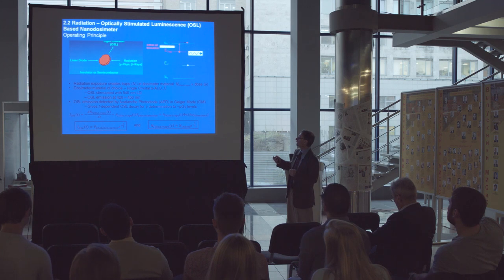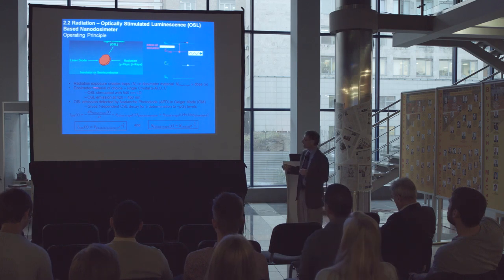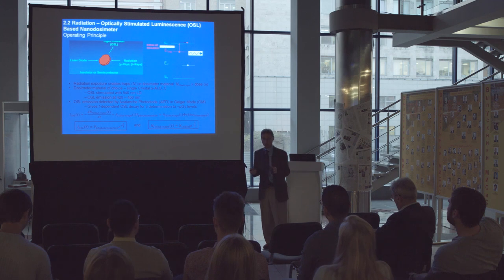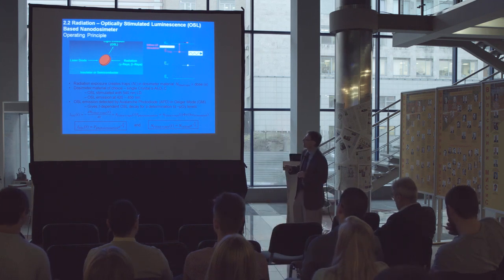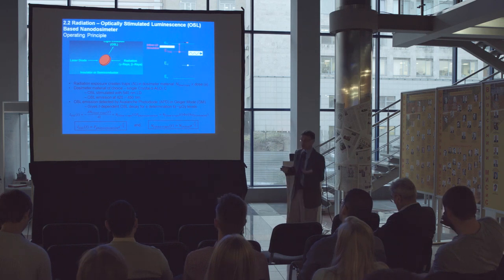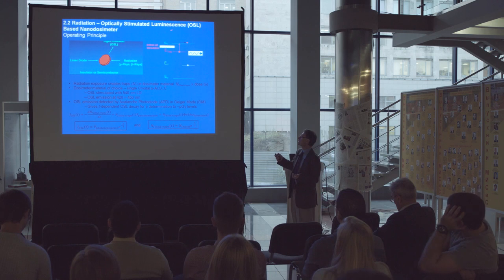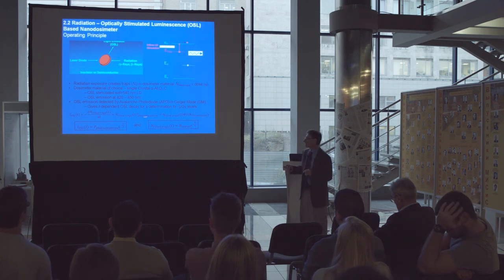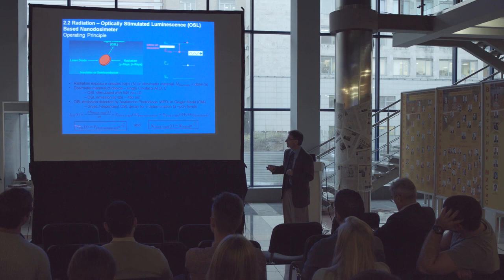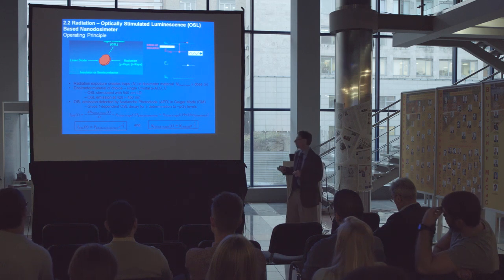Right. So I stimulate with low energy light, for example here, this 540 nanometer light, and the emitted light is higher energy, which means shorter wavelength. We call that optically stimulated luminescence, and it's around 420 to 450. The basic principle is that the rate of change of the number density of filled traps, every time one photoionizes and we capture its carrier in the light-emitting recombination process, we end up with light. So that's the probability of photoionization times the number of filled traps, with the intensity, right? There's a little differential equation here, which we can solve, which means the intensity of the stimulated luminescence as a function of time will be exponentially dependent on time, with a time constant tau.